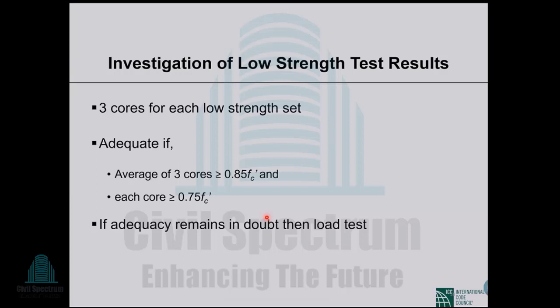In BNBC, those are not mentioned, but for professional practice, you have to study those ACI standards and literature. For lower dia cores, this is for 4-inch dia, 100 millimeter dia core. So the average of 3 cores must be greater than 85% of FC prime, and each core must be greater than 75% of FC prime. If one core is more than 75% of FC prime, then that is okay. An average of 3 cores is more than 85% of FC prime, then that is okay. So that is the standard mentioned in the BNBC, and that is directly from ACI.